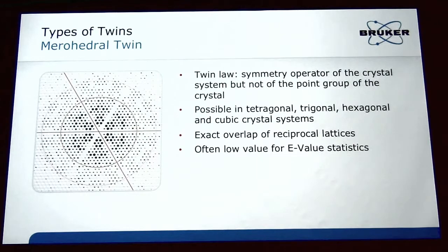But you don't find out until later, when you look at the intensity statistics, as has been mentioned today, looking for effects of twinning. And one of the statistics that George uses a lot is normalized structure factor values, or statistics based on E² minus 1 values, they're called. And they're just looking at the distribution of intensities.